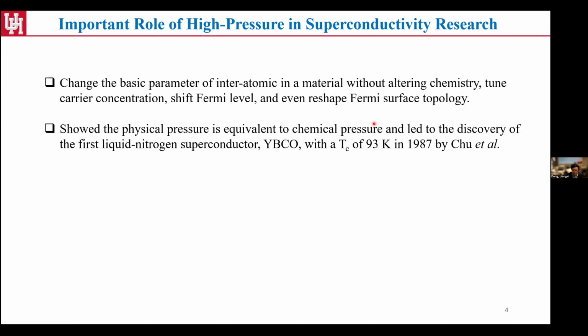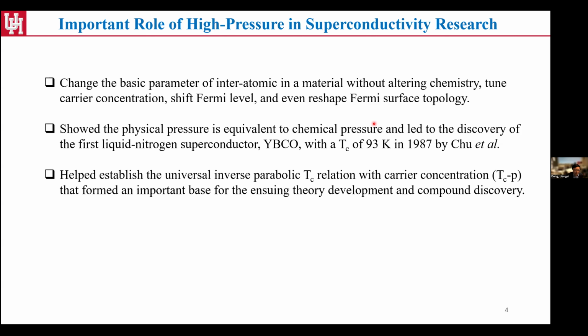That's one of the hints that led to the discovery of using yttrium to add chemical pressure that simulates the physical pressure to trigger this breakthrough. So it's this kind of mindset that triggers a lot of exciting discoveries, including YBCO back in 1987. Also, it's worth mentioning that it helped establish this universal inverse parabolic Tc relation with carrier concentration, which really formed a very important base for the following theory development and compound discovery.